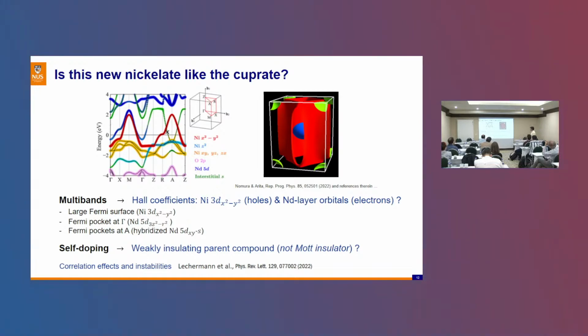So if we try to relate to what we have observed from the transport, for example this Hall coefficient, this might explain or somehow be consistent with having these multi-band structures from the DFT. So the idea of having self-doping might also lead to these differences that we observe between the cuprate and the nickelate. And that's also probably the reason why we don't have this Mott insulator parent compound. As I said before, we have this weakly insulating behavior.